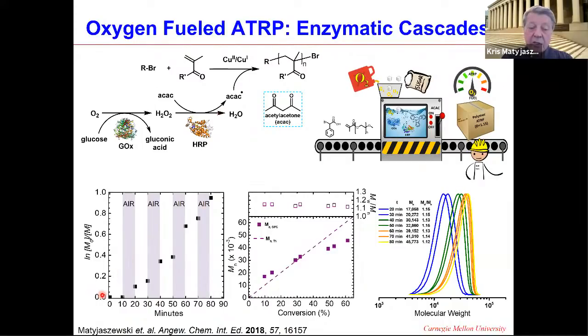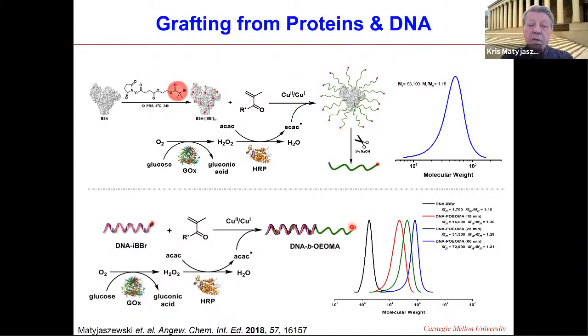You could see without oxygen, nothing happens because there is no source of radicals. Then you open it to air, polymerization starts. You close it, slows down, starts, slows down, starts, slows down, and molar mass is very nicely increased to higher molecular weight. You could see here the example of using these two enzymes, enzymatic cascade, to grow polymer chains from enzymes or proteins. We take here BSA, and in that case, by using corresponding NHS activated species, we can put ATRP initiator, around 30 of them, and then grow polymer chains and eventually digest this enzyme, analyze molecular weight, and check how good control of molecular weight and dispersity it is.